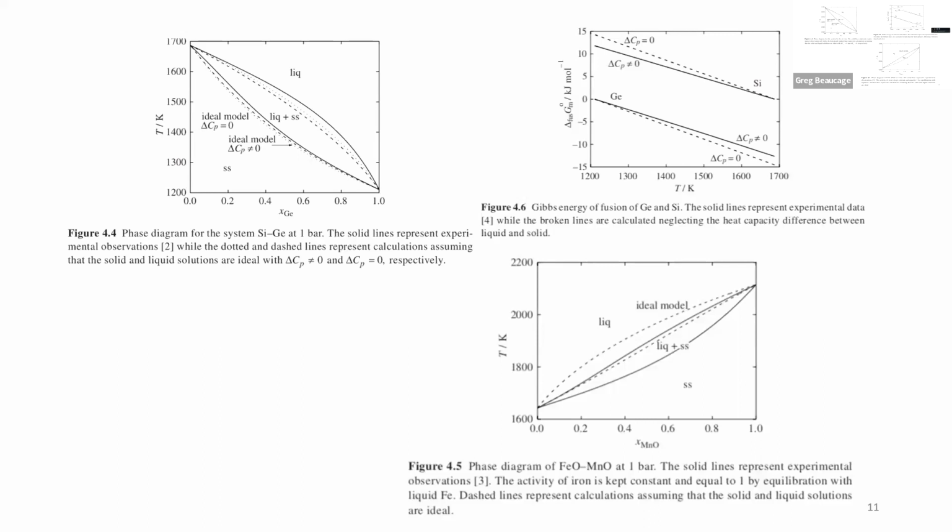Anyway, so it's that business, and then this shows the deviation from using actual heat capacity and not letting the heat capacity change. This is for a more complex system, so the situation gets worse. So this is a pretty simple thing, like diamond cubic, a pretty simple crystal structure, and the two things have almost the same size. So if you start looking at things that have polarity, like oxides, then things aren't as nice, right? So the model calculation kind of matches.